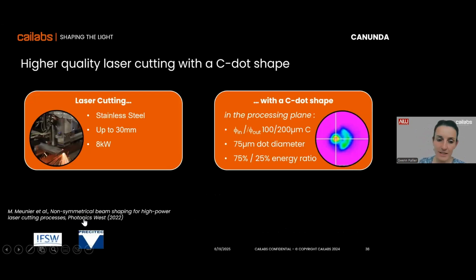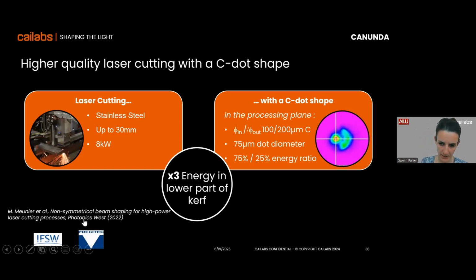In the case of cutting, it's also not a big business for us, but we did work at least on one project with this C-dot shape. And the whole idea is to actually cut very thick parts, but having the same energy all along the curve, which is not the case when you are using a standard Gaussian beam.